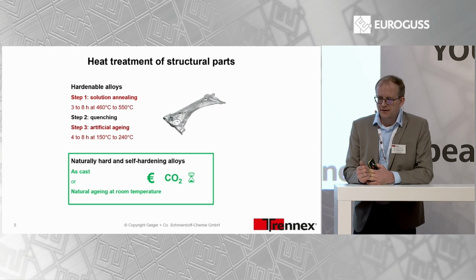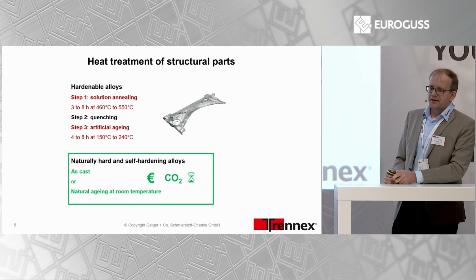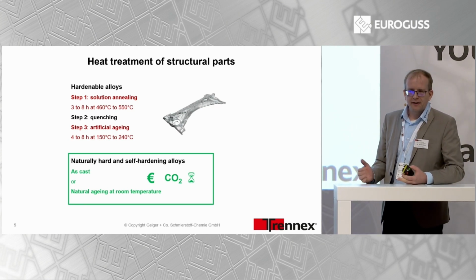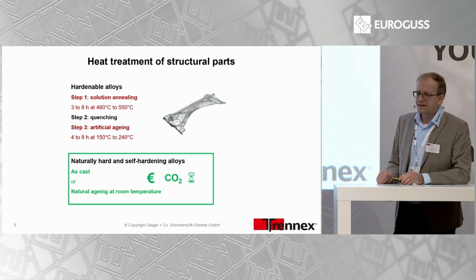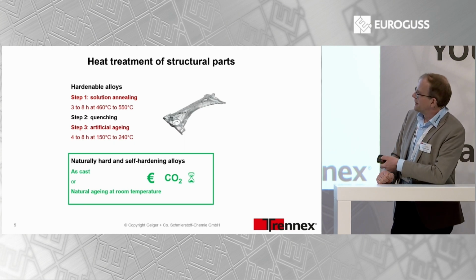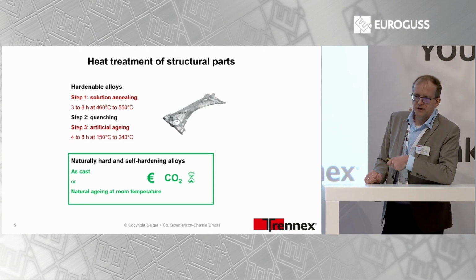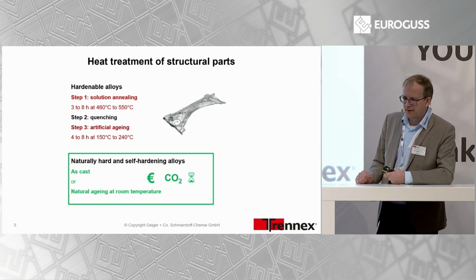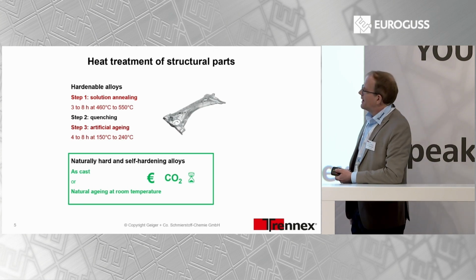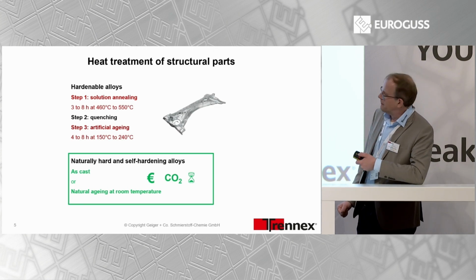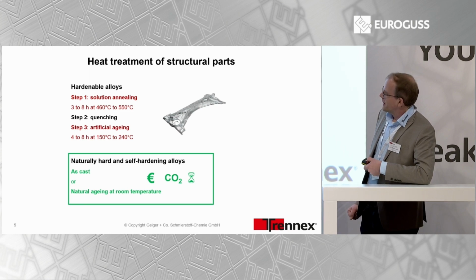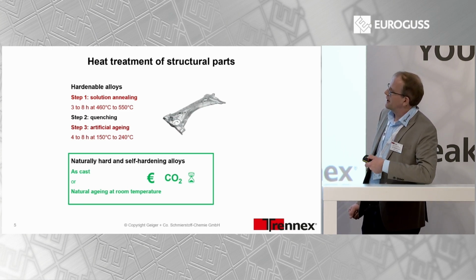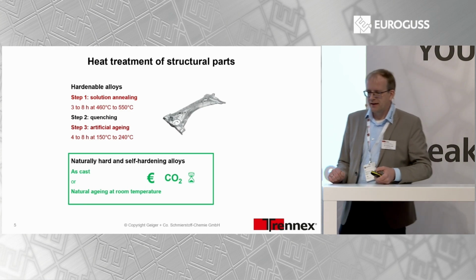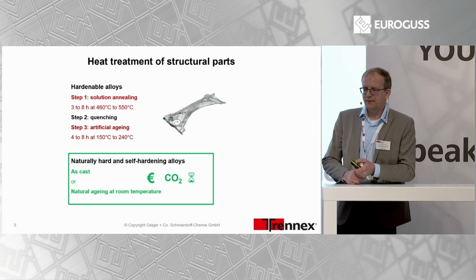If you choose a naturally hard or a self-hardening alloy, that means you do not have these steps before. You can use the casting really as cast, or you have a natural aging at room temperature. This is a self-hardening alloy. This means you save a lot of costs, and also carbon dioxide, because you do not have these energy-intense steps before.